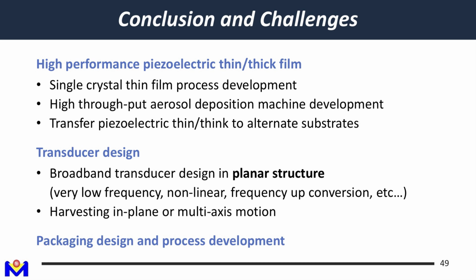For example, we are expecting even better, high performance piezoelectric thin film, especially like the single crystal thin film PLD process. In the beginning, we had very high expectations for this process. But in the end, we found the following fabrication is so difficult. And the aerosol deposition method that was developed in my lab is already quite mature. But when we talk to the industry, they ask, can you have a high throughput, mass production machine? I say no, because we built the machine by ourselves. So we still need some time and investment to get this kind of mass production, high throughput machine.